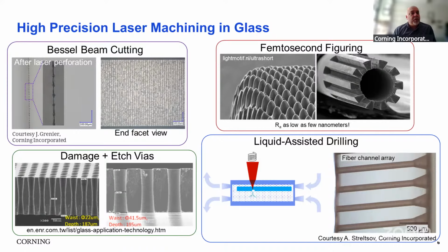I'll make a little plug here for precision machining in glass. You can use, say, Bessel beams or these non-diffractive beams to cut very rapidly through glass, in a process that's almost like perforating, as you would get in a paper towel. It's a very rapid way, a meter a second or even more, of cutting very thin brittle materials such as glass. You're looking at damage and etching of vias. You can do this by creating damaged sites in an array, and then use etching to expand those damaged sites into vias. This can be used for, say, the electronics industry.